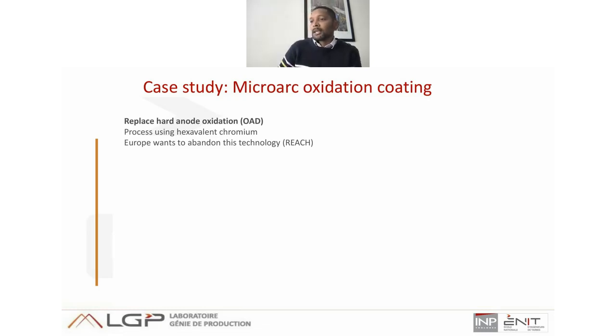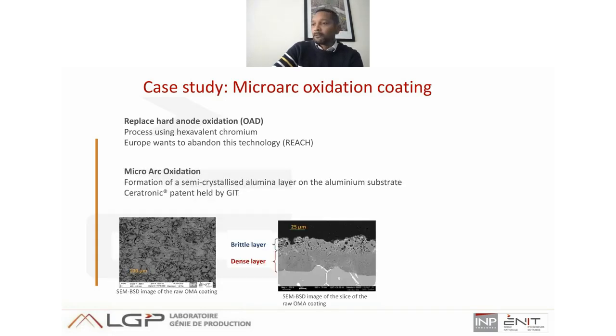However, this coating uses hexavalent chromium, and Europe recommends abandoning this process through the REACH regulation. GIT has therefore launched the production of a coating that respects the REACH regulation. This is micro-arc oxidation, and I will call it OMA. The micro-arc oxidation permits the formation of semi-crystalline alumina on the surface layer. This alumina layer has two parts, a dense part located directly above the substrate and a brittle part close to the surface.